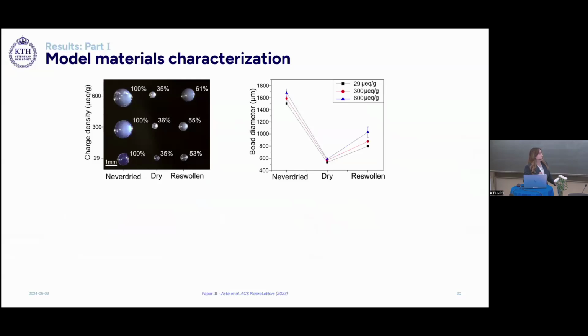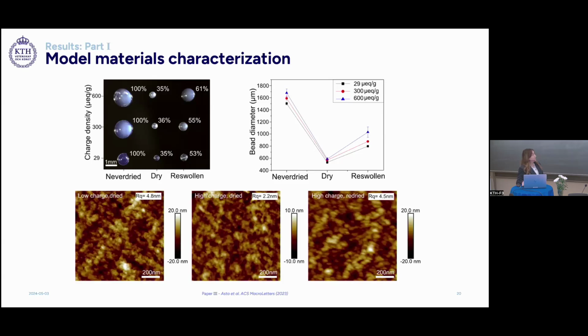And these cellulose beads have a diameter of around 1.5 millimeters in wet state. When they dry, they shrink to around 35% of their original size. And when re-swollen in water, they swell back to about 55 to 60% of their original size, depending on the charge density of the cellulose. They have a nanometer smooth surface measured with AFM, which makes them excellent for adhesion studies.